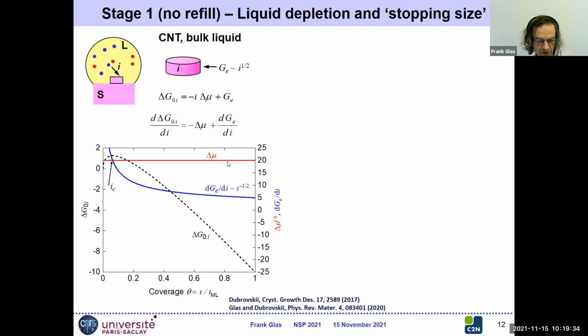Delta mu is constant as a function of coverage, so as a function of atoms transferred from the liquid to the solid. But we know that this edge energy varies as a first approximation as a square root. So here in blue, we have the derivative of the square root. And of course, the critical size is when the derivative of the square root becomes less than the chemical potential. So they become equal. Here we have unstable equilibrium. And after, this derivative is less than the chemical potential. So that's simply the translation that adding an atom to the island will be interesting in terms of energy. And correlatively, the work of formation itself increases, has a maximum, and then decreases. That's what we have seen before.